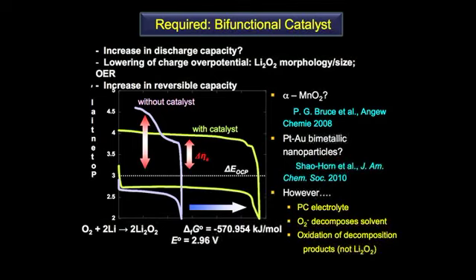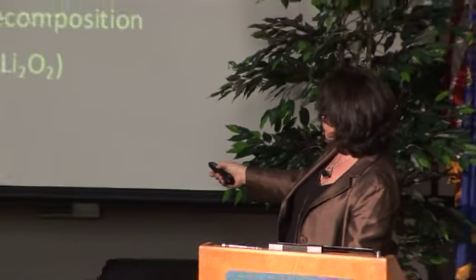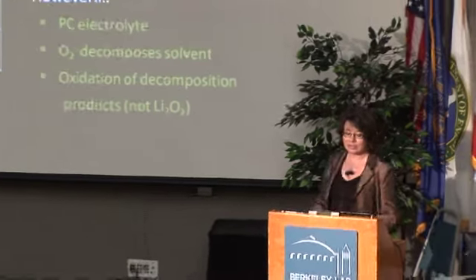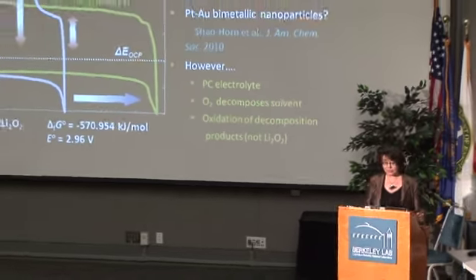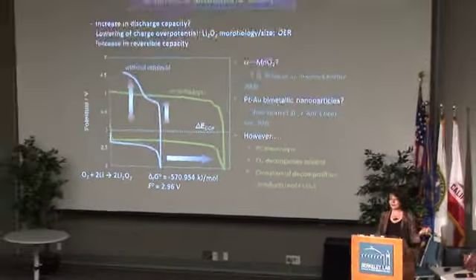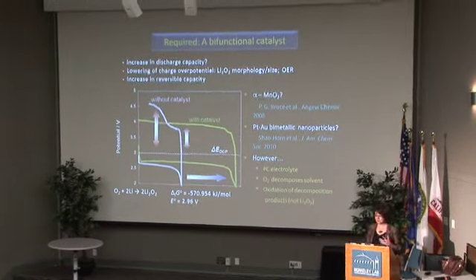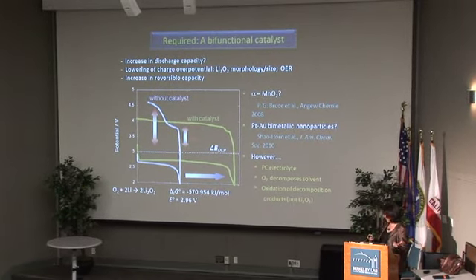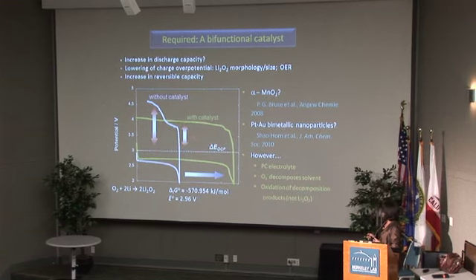Alpha MnO2 reported by Bruce, the platinum gold particles reported by Shao-Horn's group. Unfortunately, all of these studies were done in what we call BPC, which is before propylene carbonate, or before propylene carbonate was discovered as having problems. And so they were carried out in a propylene carbonate electrolyte where the oxygen decomposes, the superoxide decomposes a solvent. So the reversibility in these systems is not Li2O2 being charged, it's all those nasty products.